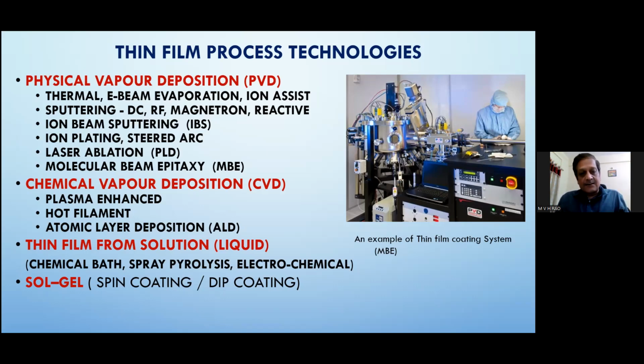And then the second constituent is introduced in the next round. That also forms one uniform monolayer on top of the first, and each atom from the first layer and the second layer react with each other and form the compound. So it happens in cycles. The beauty of this process is that it happens layer by layer. So we can make epitaxial films just like MBE. Here also multilayer films are possible.